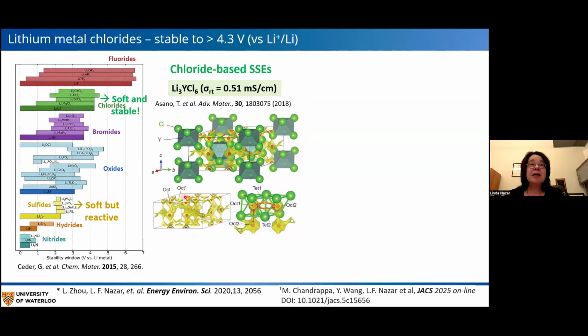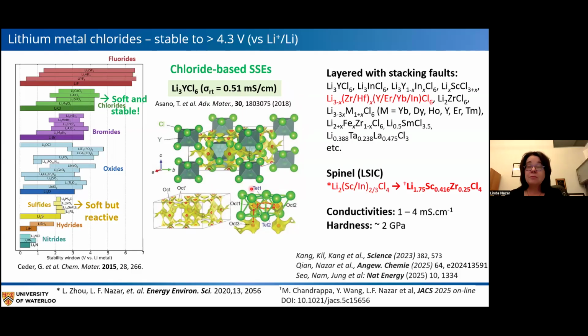And this is just an example of the lithium yttrium chloride structure. And you can see that there are 2 sites that lithium occupies, both octahedral and tetrahedral, in this lattice. And that in itself causes a few problems. So since 2018, when this lithium yttrium chloride was first published, there have been a lot of materials published, way, way too many for me to decorate the slide with. So I've just listed a few examples here and our contributions in red.